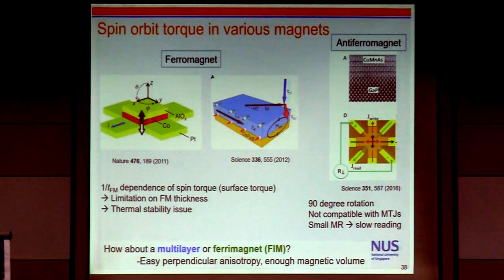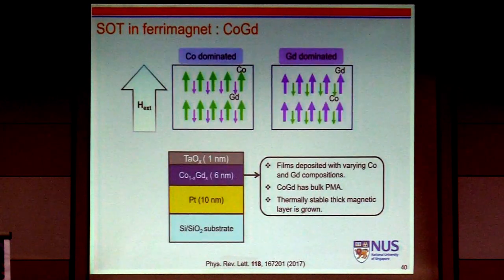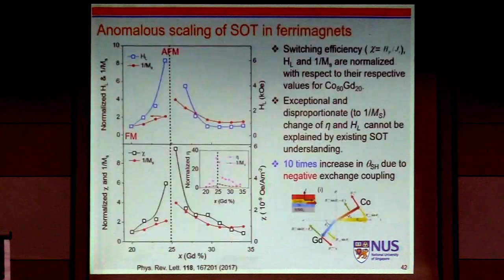So anyhow, in my view, we should immediately utilize a multilayer or a ferrimagnet as the next generation technology, because I'm working with the GlobalFoundries guys. So we are doing this experiment with the ferrimagnet cobalt gadolinium. Depending on composition, it can be cobalt-dominated or gadolinium-dominated. And in fact, we can study all the way from a ferromagnetic-like phase to an antiferromagnetic-like phase. So with the platinum spin current, we can study those.